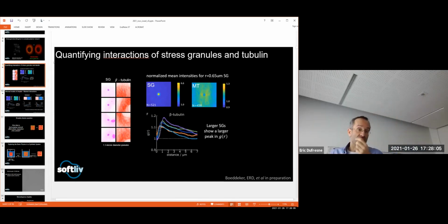Yes, and that's an excellent point, actually. There's a few things, and I thought about those questions more in the context of the polymers than in the cell. I think in the cells, the filament networks are still so dilute that I don't think they would really seal things off very much, and also because the strains are very low in the cell. We might open up a pore that's a few times the mesh scale, not 1,000 times the mesh scale. So one idea that Rob has been thinking about a lot is that when you grow these things to a factor of 1,000 and you're stretching all these chains right next to each other, they're being stretched, they're being aligned.